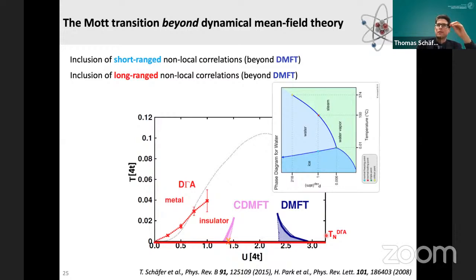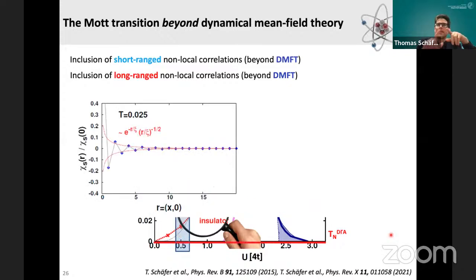And how can we quantify this? Well, we, for example, can zoom into this so-called weak coupling regime of the phase diagram and calculate the spin-spin response function. In this case, the spin-spin response function is showing an antiferromagnetic behavior because the sign of this function is changing from lattice site to lattice site if I would make a cut. This is the first thing which we see. The second thing is that at temperatures above this crossover line, we have a so-called correlation length, which is this damping factor of this curve, of 4 lattice sites, which is not super large.